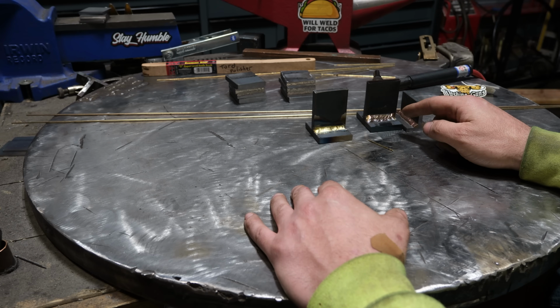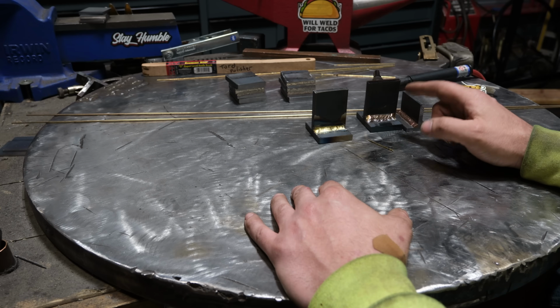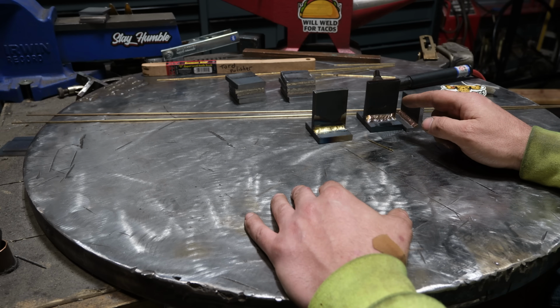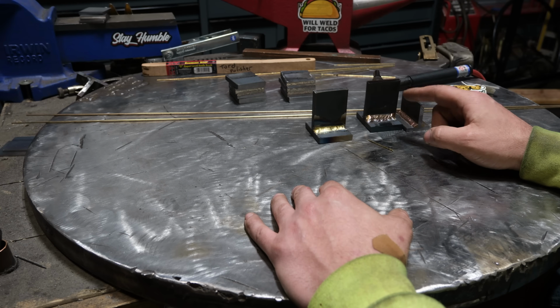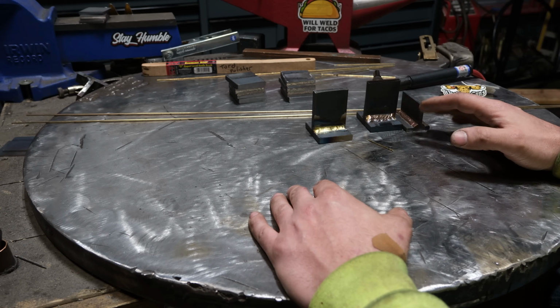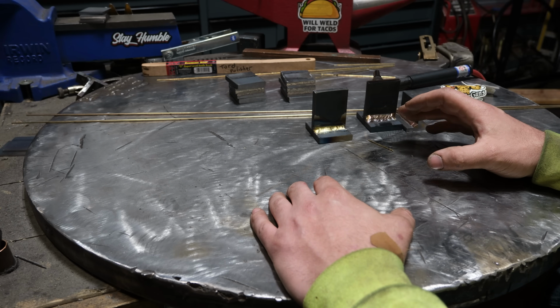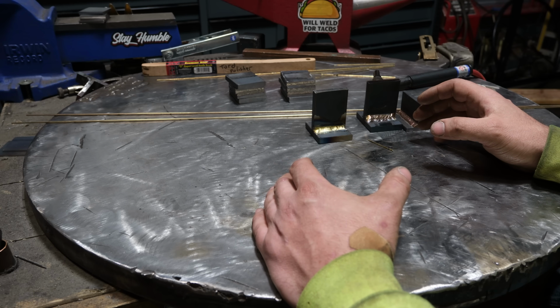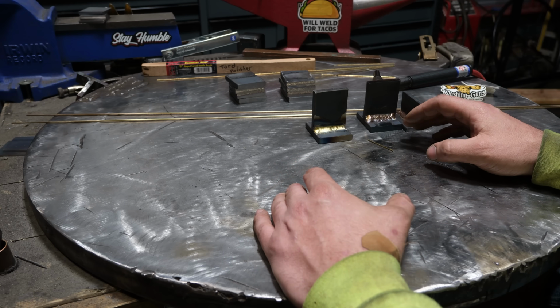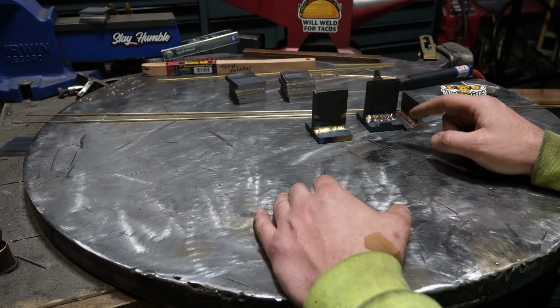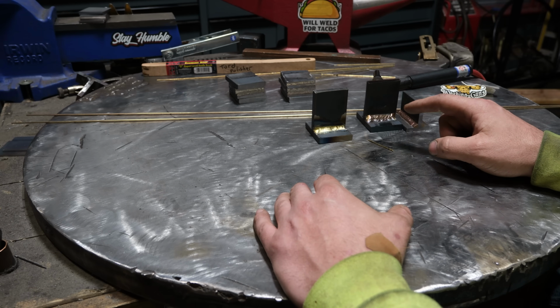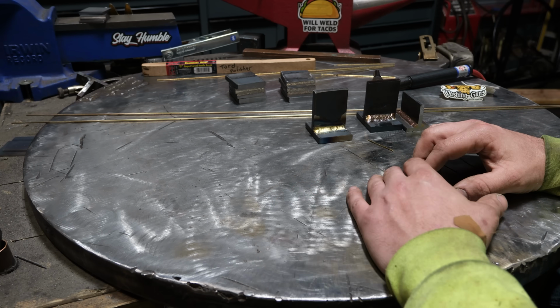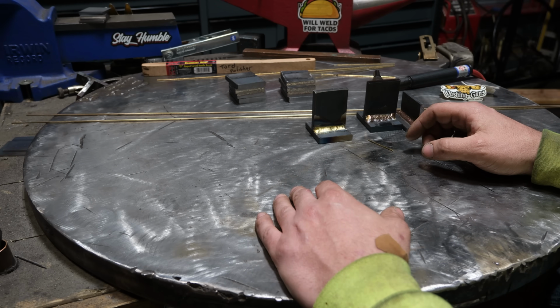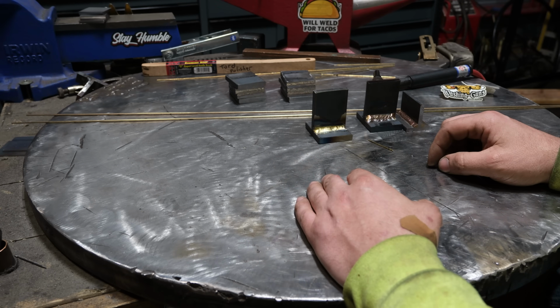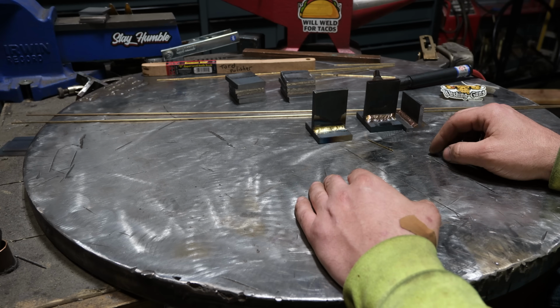And don't quote me on it, but I believe certain Formula One cars actually used TIG weld brazed or even torch weld brazed chromoly parts on the suspension. And that is likely because the heat affected zone is so much smaller that you don't have that brittleness. Because anyone who's welded on chromoly and a lot of tool steels and a lot of specialty alloys knows that if you don't heat treat the part when you're done, the weld will never fail, but the part will crack right near the weld under stress. So that's why it pays to have some of this stuff around, because it can help you out in a pinch solving problems.